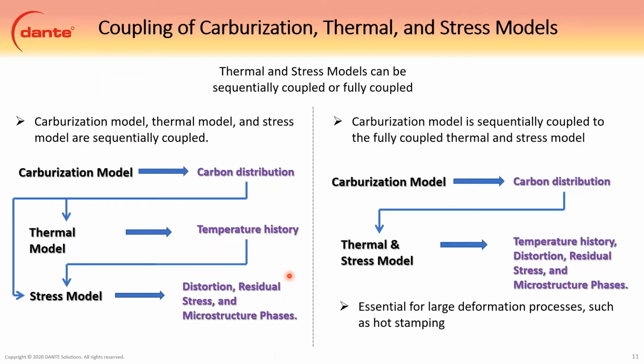All right, so the way that we normally run these is we sequentially couple them, which is the figure on the left. So we'll run a carburization model and get a carbon distribution. That carbon distribution will then get mapped to what we call a thermal model, which will be the actual heat treat processing steps. That'll get us our temperature history, which is then read by the stress model, which gives us the distortion, residual stress, and microstructure. So it's a three-step process, and because the distortions are small, it's possible to do it like this.